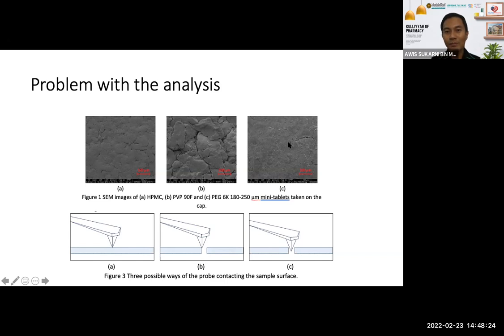You can see it's quite smooth, with fewer cracks, and even the cracks are quite small. The HPMC is also quite smooth, but you can still see some obvious particles here and here. Based on this picture, we hypothesize that there are three possible ways the probe contacts the surface of the sample. The first one, of course, is contacting directly on the surface of the sample. When this happens, it will show you a proper reading.